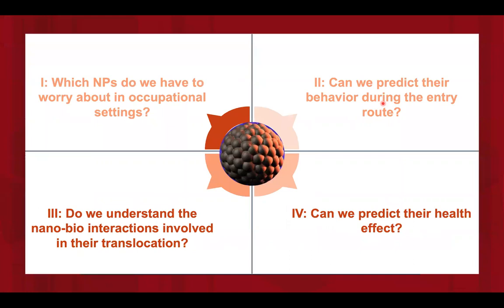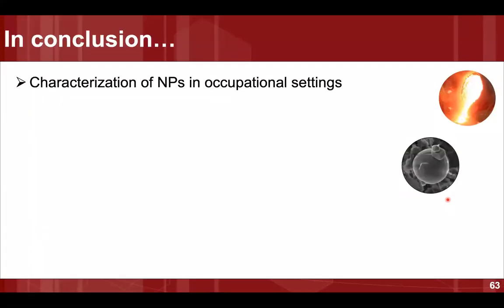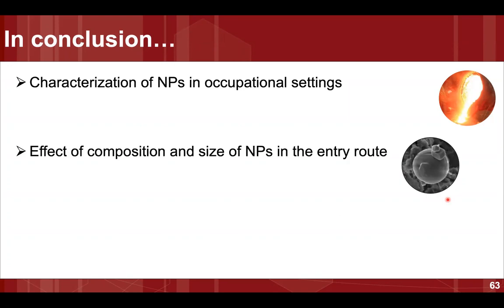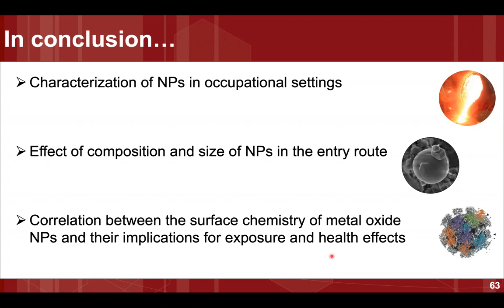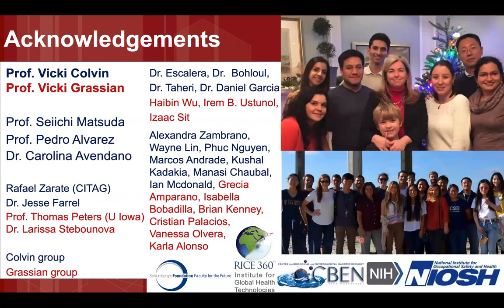And I also have other projects where I look at interactions with proteins and amino acids. The idea was trying to predict where they will end up. I'm not going to talk about that because it's not part of the story that I want to tell you. But in general, during my postdoc, I characterized nanoparticles in occupational settings, particles that workers are breathing. We found that they agglomerate in these conditions, and we tried to correlate the surface chemistry of these to the implications for health. And all this was work that I did during my PhD and postdoc.